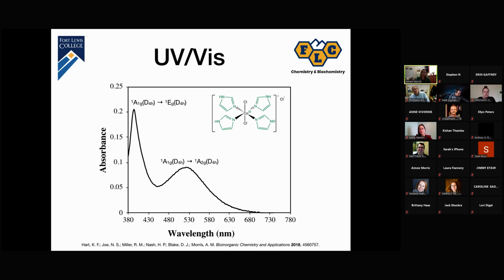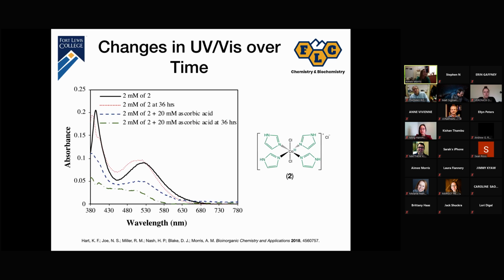The other thing we were seeing, so as we took this UV-vis of the compound, we noticed that there was a visual color change happening within our actual cuvette. And so I'll just show you kind of a before and after of that. But so we took the UV-vis of this and then we just left it there and we took another UV-vis 36 hours later. And what you'll see is a blue shifting of those two maxima. And so the blue shift is likely due to ligand exchange.